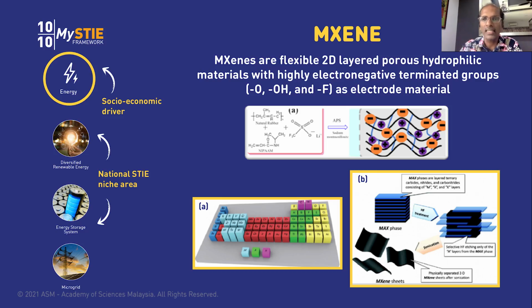As mentioned earlier, an energy storage device comprises two main components, the electrode and electrolyte. To achieve a high-performing energy storage device, selection of materials is very important. Hence, for our supercapacitor, we use a novel electrode material known as MXene. MXenes are flexible 2D layered porous hydrophilic materials with highly electronegative terminated groups as electrode material.